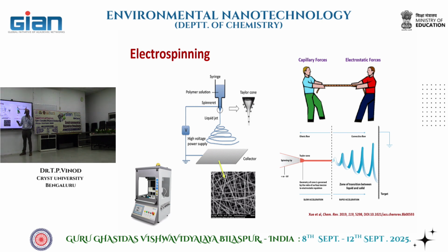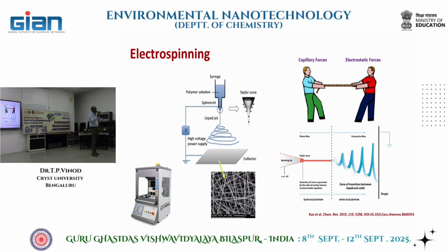You won't see nanofibers. You will see a film. You will see a membrane, which when you take to the SEM, which is usually required, you will see structures like this. So what's happening when the polymer solution is pushed down and electric voltage is applied, that's a DC voltage, two opposing forces are there. One is capillary force. Capillary force wants to retain this droplet in the spherical form in order to have minimum energy, right? So in order to minimize the surface area, in order to minimize the surface energy, it wants to remain as a droplet.